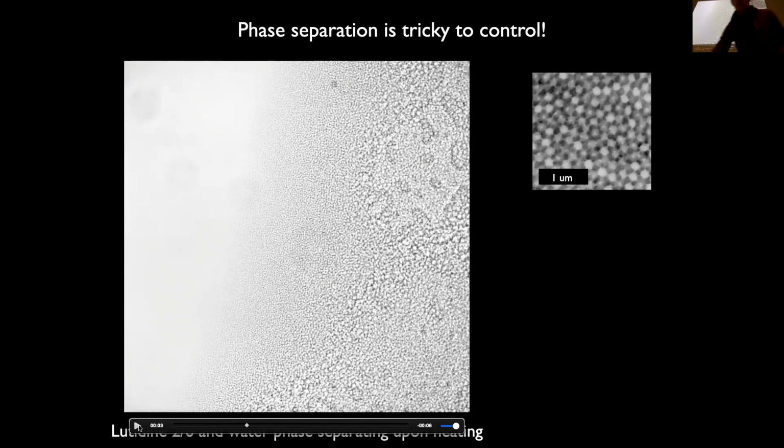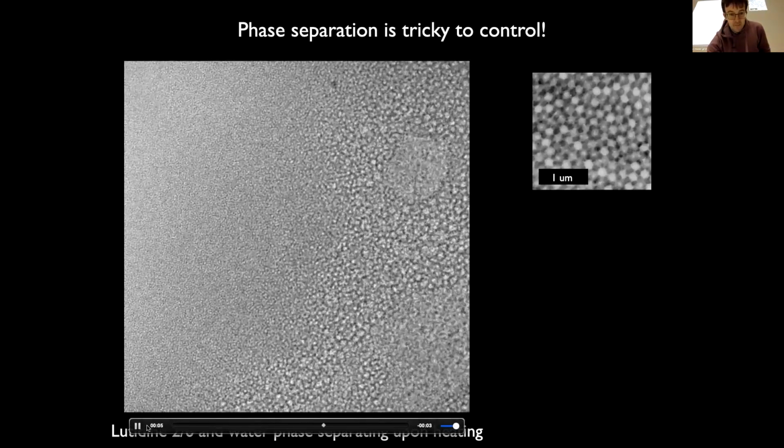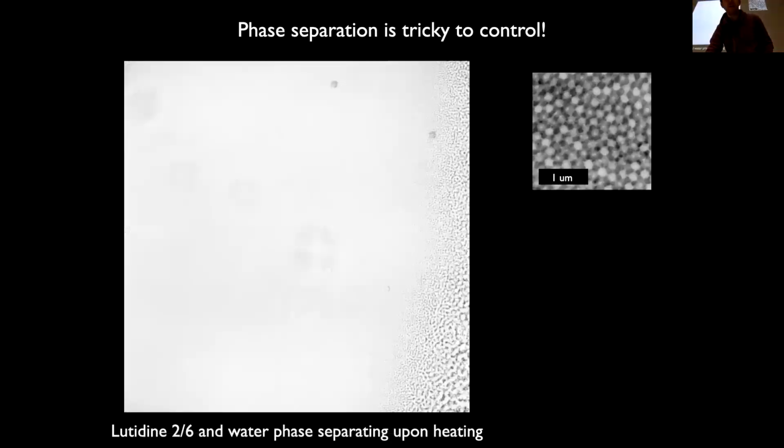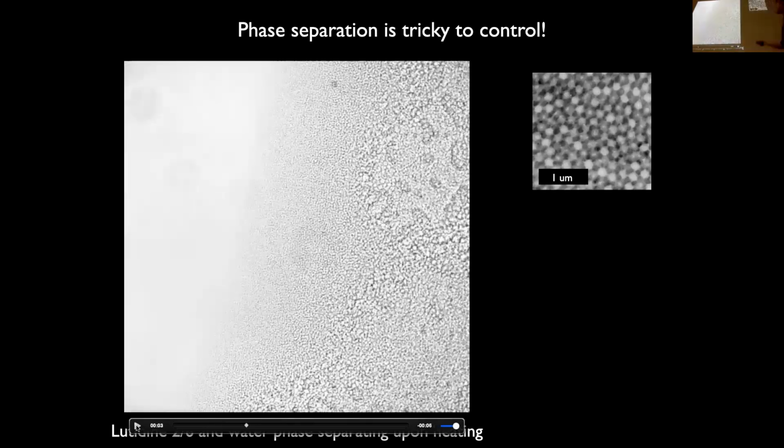It's about 500 microns from one side to the other side of the video. So you can see on the right-hand side now, you've got a lot of mess that's starting to come out. The reason we're losing this is because these droplets of liquid are just coalescing with each other, and it just coarsens the pattern. There's another thing called Ostwald ripening that I'll come back to, but in this case, it's not really super relevant. So what we want to do is keep this nice uniform length that comes out at the start, but not have all of the coalescence that's causing us this mess at the end of the phase separation.